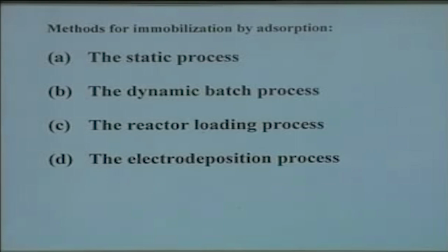Of course, it takes a very long time, and that is the process very often people use in laboratories. The yields are also much lower, particularly for porous carriers, because the diffusional limitations without agitation do not allow proper adsorption. And of course, one of the most disadvantageous situations in the static process is that the loading of the enzyme is not uniform over the carrier. Even if you allow for a long period, the loading is usually not uniform.